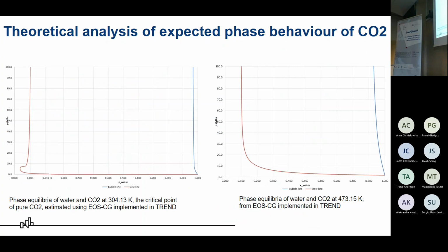Here we have two charts for phase equilibria of water and CO2 at the critical point of pure CO2 and at 200 degrees. And we see that the solubility of water is really low, but here it's around 10%. So the composition is really important at the temperature.